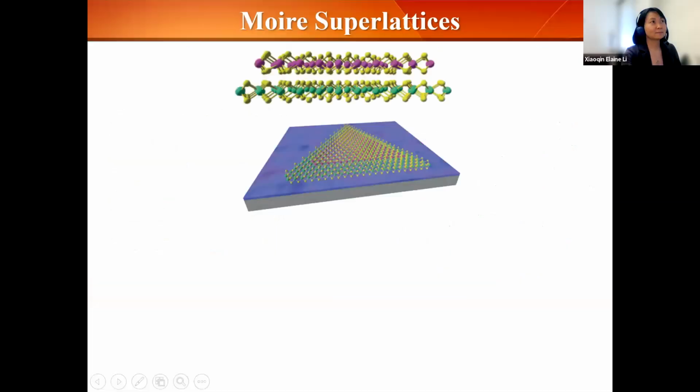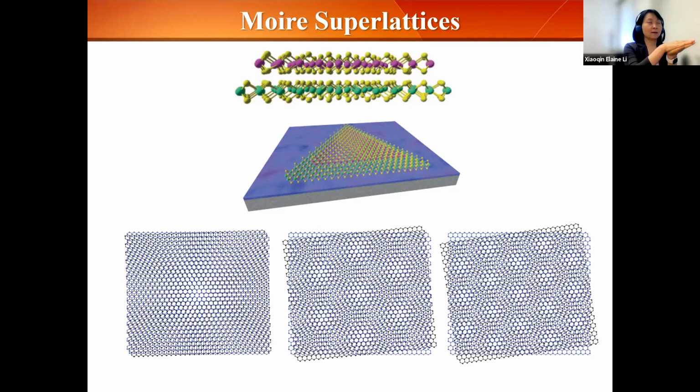All right. So my own group and many others have started to move beyond studying a single monolayer semiconductor. Many of us have learned to stack two monolayers together vertically, and to do so in a controlled manner, controlling the relative twist angle between the two layers. As you can see, an in-plane superlattice develops that we call a Moiré superlattice, and the size of this unit cell is controllable. The bigger the twist angle, the smaller the supercell.